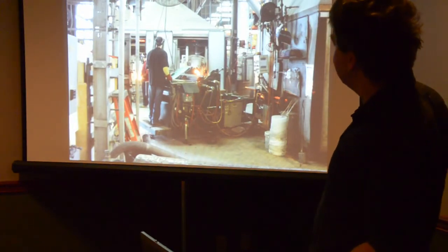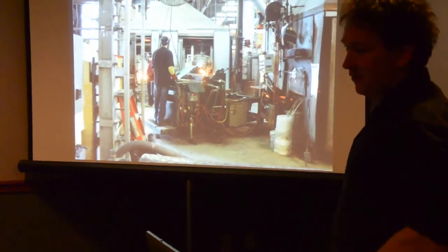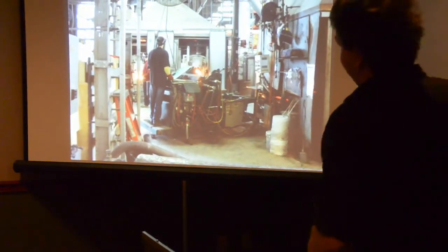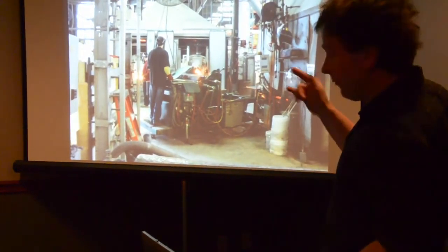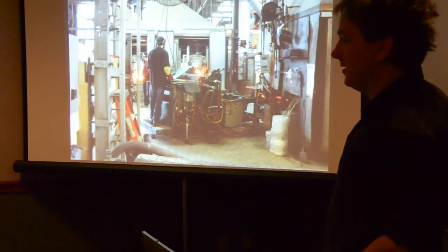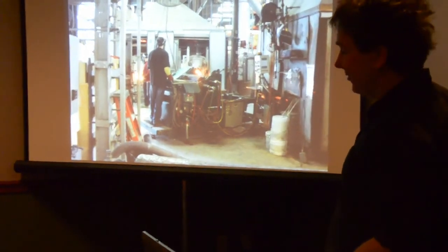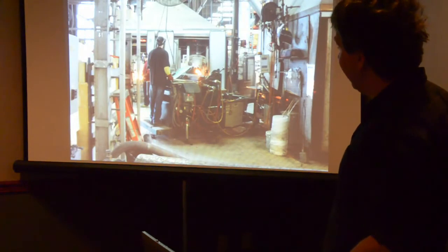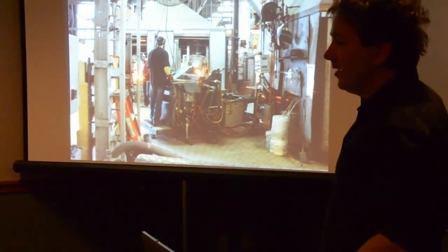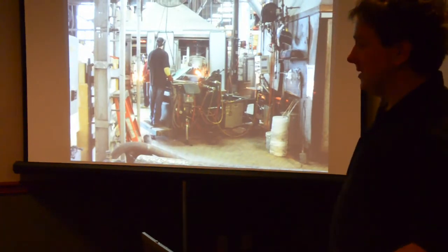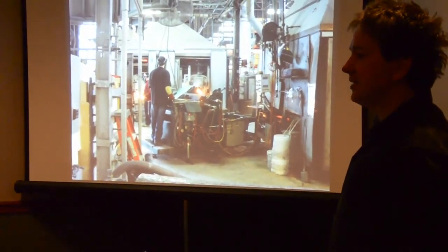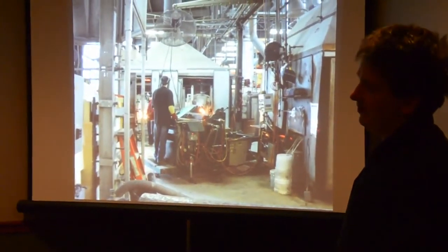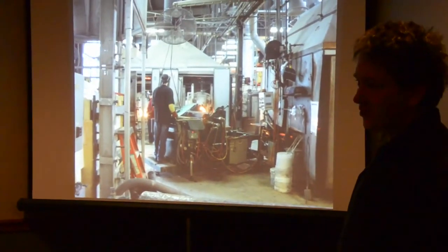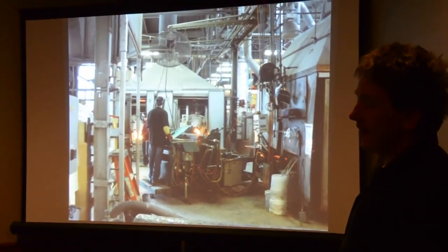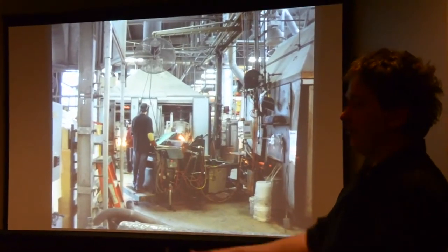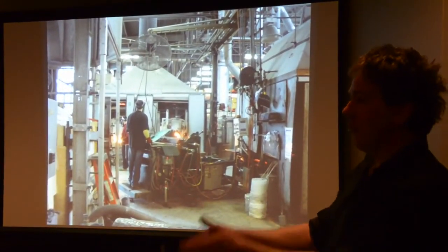It's very important that those glasses have the same expansion coefficient, or all that glass is going to be scrapped. And in fact, these professionals, they scrap 30% of what they make. I learned that while doing this. It was impressive that even after all this time, 30%. And they've got some nice polarized screens to check for stresses. What's that? They reuse it then. Well, they say they reuse it, and technically that's true, but you can't put it back into the pot. No. Because now you've got a muddy color that you're starting with. You have to start with a pure color.